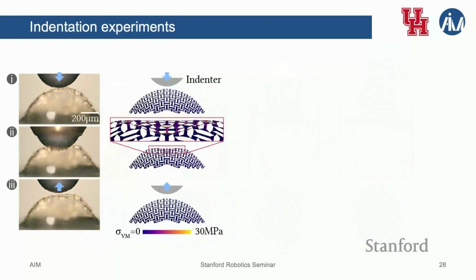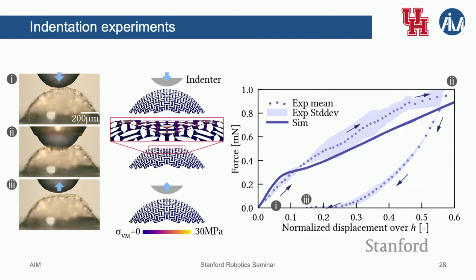And because it's a stable shape, we can of course push on it, right? So we can mechanically load that surface as if it was built in that domed shape, and it does. So we can indent it, and then when we let go, it pretty much recovers to its original state. There's hysteresis here. So there's quite a number of ways energy is dissipated as you push on this shell, but otherwise it recovers pretty much to the original state.